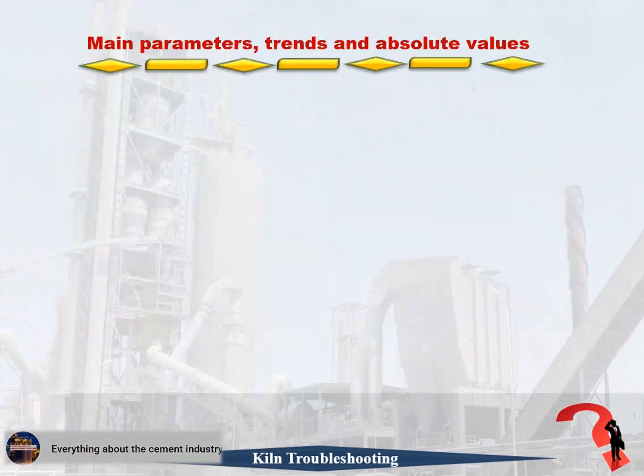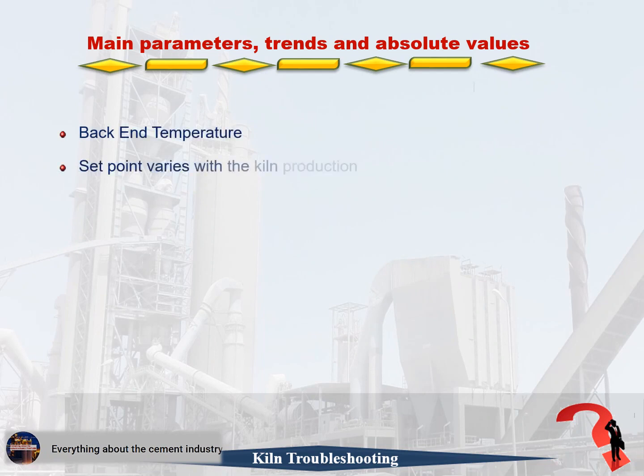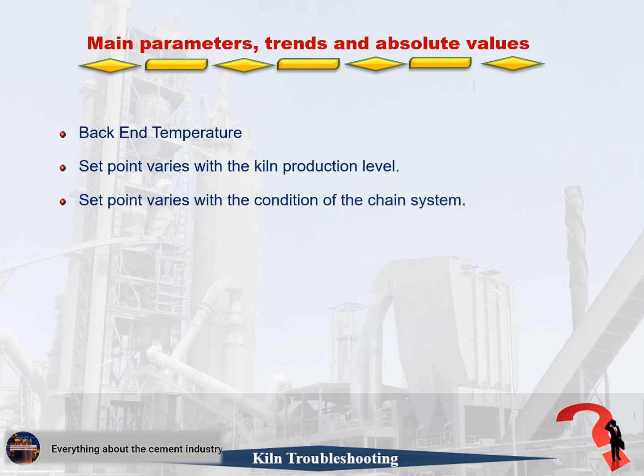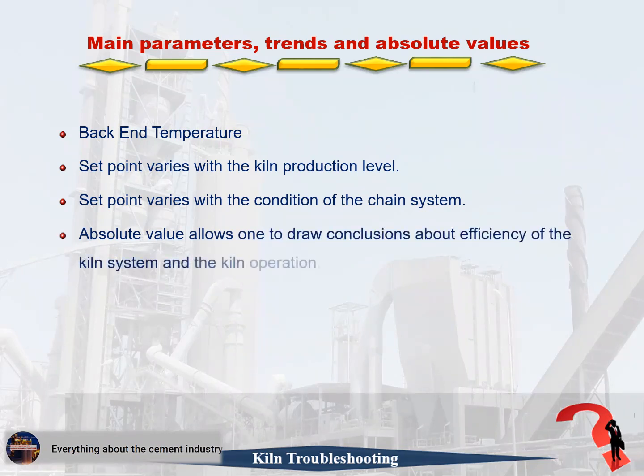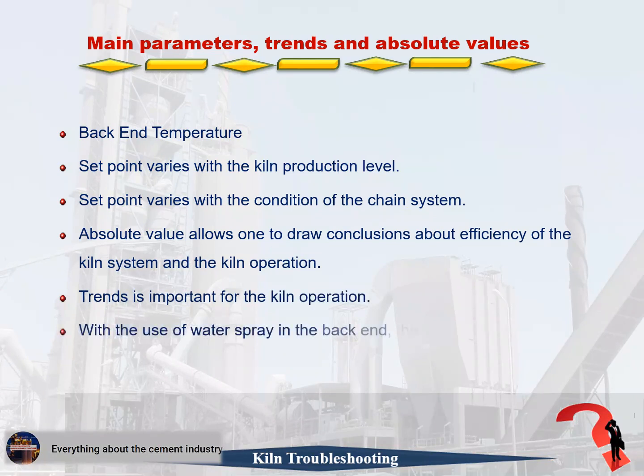Main parameters, trends, and absolute values. 1. Back-end temperature. 2. Set point varies with the kiln production level. 3. Set point varies with the condition of the chain system. 4. Absolute value allows one to draw conclusions about efficiency of the kiln system and the kiln operation. 5. Trends is important for the kiln operation. 6. With the use of water spray in the back end, the water volume will show the reactions of the back end temperature.